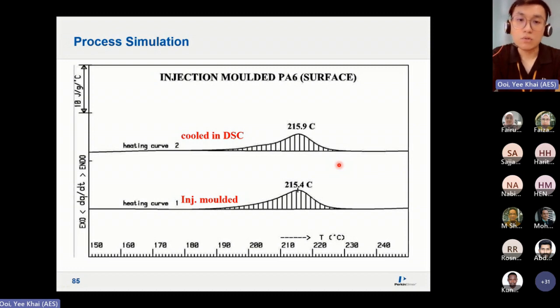So now in industry, usually for polymer engineering, they wouldn't cool down slowly, for example. Usually, for example in injection molding, they will do quench cooling. So this is the product coming from the injection molding. This is the melting peak, meaning the plastic or the polymer is going to get melted, and then after that quench cooled at a very, very fast rate. And then this is the result. So we can use DSC to simulate that as well for the PA6 nylon.